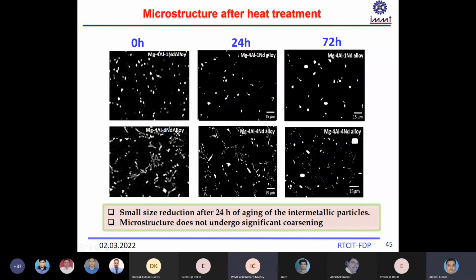So here you can see the different aging times, and how the microstructure is changing. This is the magnesium aluminium 1Nd alloy, and this is 4Nd. The top one is the magnesium 4 aluminium 1Nd, and the bottom is the magnesium 4 aluminium 4Nd. So you can see the different aging times. This is before aging, and this is 24-hour aging and 72-hour aging.